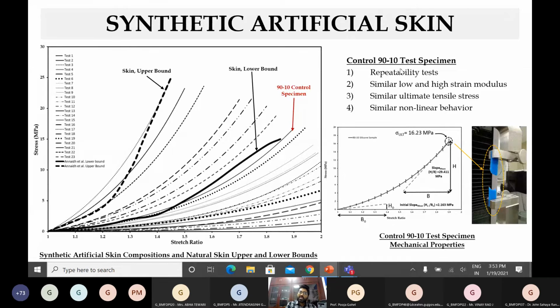So this one, which is called 90-10, 90-10 meaning basically 90% of one chemical and 10% of another, which we narrowed down to. This is all patent protected. So we came out with this 90-10 composition, which we thought would mimic the bottom line or the skin lower bound. And we thought we could play with this and look at some of the repeatability tests. So all the error bars are basically pointing at the repeatability test. So we can see the synthetic material is extremely repeatable. So that's number one.